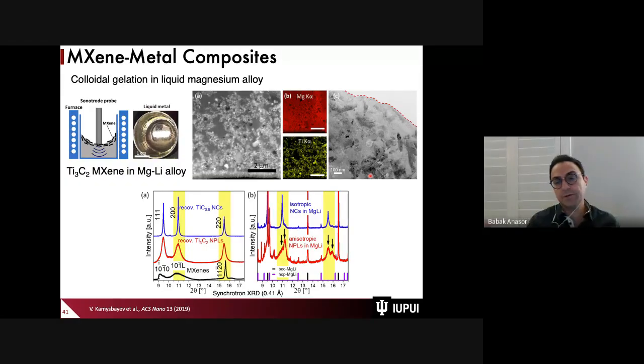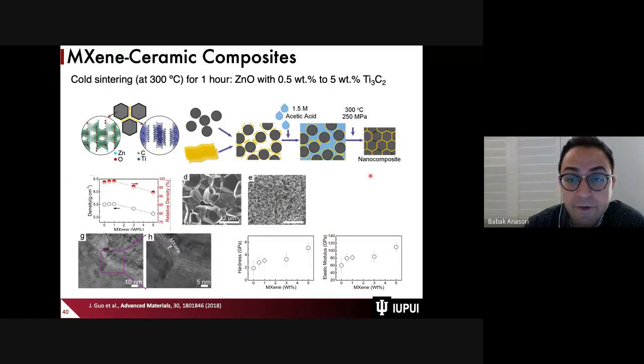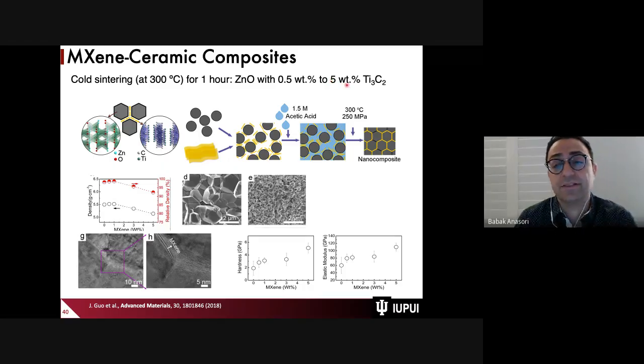Now, you might say, well, we can also just simply put titanium carbide instead of going the route of MXene. Yes, we can. But the advantage here, like all the previous slides that I mentioned, is that we're talking about only 1 nanometer thick of these additives and reinforcing materials. So, for example, here we're only talking about half a weight percent to a maximum of 5 weight percent. I believe 5 weight percent is already too much. We have to keep it below 1 to a maximum of 2 weight percent.